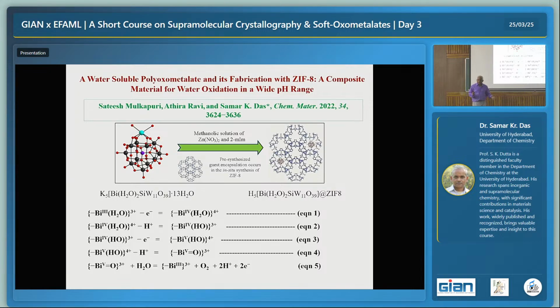It doesn't decompose. First of all, it is heterogeneous now. It is not soluble because it is inside. If you remember, earlier we told you the cluster was 1 cluster per MOP. Here we got 2 clusters per MOP. Again, we have no control. Even if we put extra, it always takes, in this particular case, 2 clusters per MOP. So we have kept one functionalized bismuth POM, polyoxometalate. How did we functionalize? With a bismuth aqua compound. Why did we do that? The whole moiety is inactive, but bismuth is very active, and we can get water oxidation.